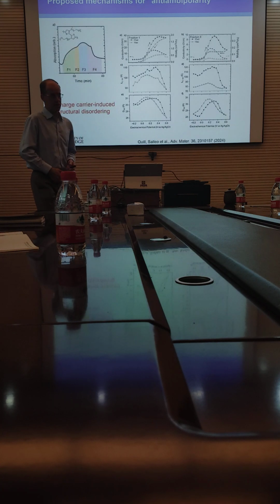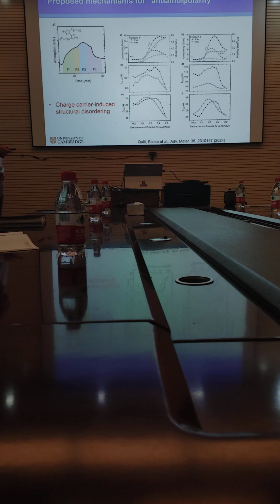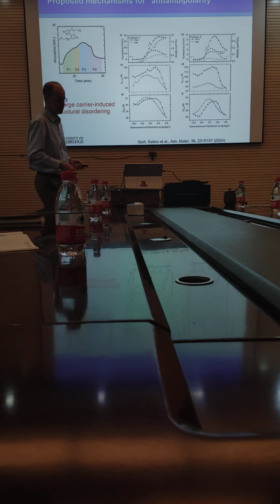That's not the only explanation that's been given. This is some recent work from Alberto Salleo's group, who's shown that you also need to think about the microstructure. If you go to these high doping levels and push beyond the peak in the conductivity, they found that in P3HT or in these thiophene-based polymers, the microstructure actually degrades. The polymer is no longer very crystalline. You get a lot of disorder incorporated into the polymer at these high ion densities, and that might be a factor that you need to take into account when you try to explain this conductivity.